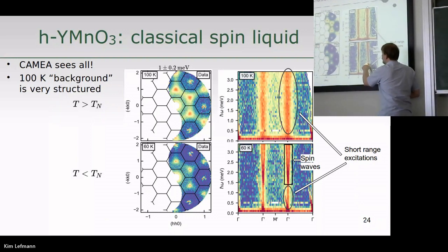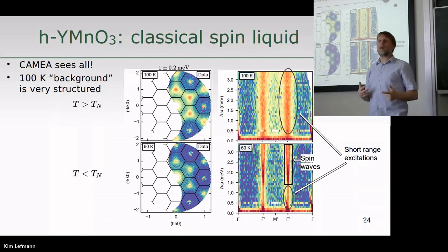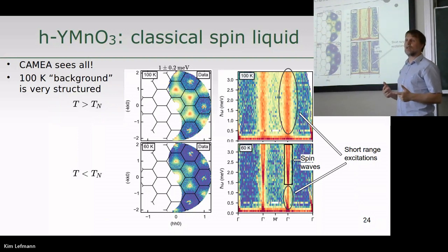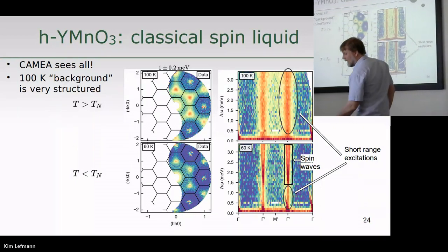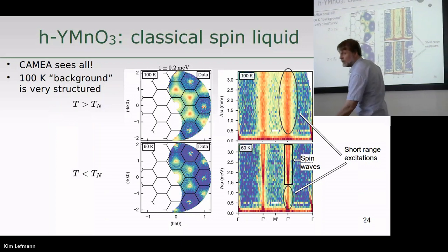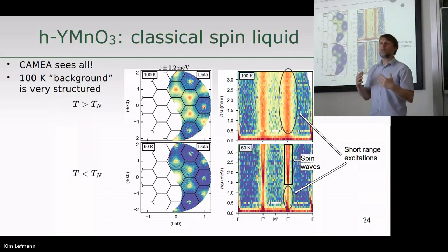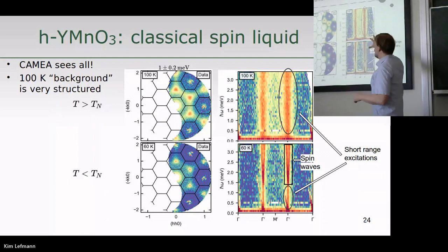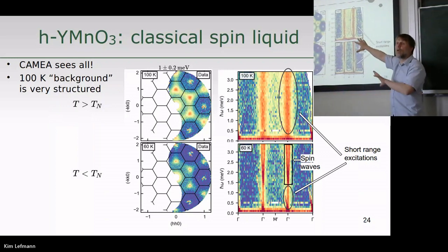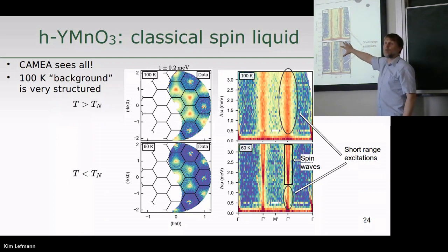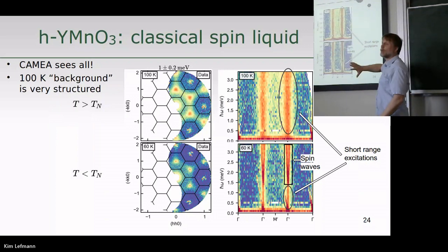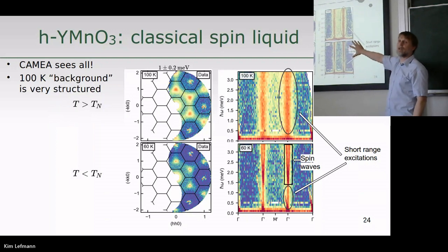But hey, there is also this thing that really reminds us of this. So there is something, some new excitations. We didn't even invent a name for it yet. But there is a new type of excitations that are not spin waves, that live in this system. Or as we believe, it's because it's a frustrated system. And a little teaser, we have studied three other frustrated systems and found the same thing. And we have studied a few non-frustrated systems and found no sign of this at all.